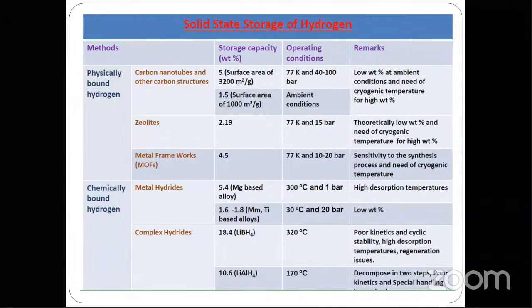If you go for solid state hydrogen storage, again we have different materials to store the hydrogen at various operating conditions. So you can see the physically bound hydrogen. You can use carbon nanotubes and other carbon structures, and you can also use zeolites, and you can also use metal organic frameworks, MOFs. So the storage capacity is different: 5% for carbon nanotubes, 2% for zeolites, and 4.5% for metal organic frameworks, MOFs.